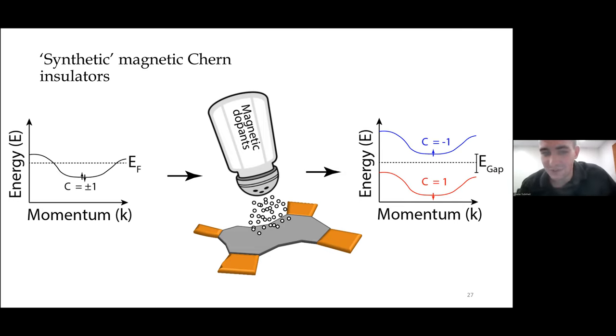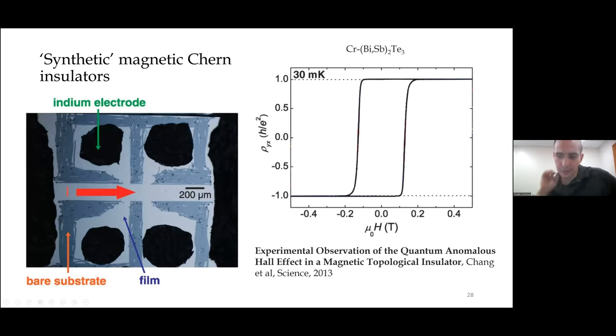So what do I mean by synthetic Chern insulator? So early in the days of the study of these systems, theoretically, there were a variety of proposals for realizing them in experiment. And the first one that ultimately succeeded was this so-called magnetic doping idea. The idea there was to take a 3D topological insulator, make a very, very thin film of it, and add magnetic dopants. So sort of extrinsically turn the system into one that has strong exchange interactions, thereby realizing a Chern insulator. So the idea here is that you start with Chern bands, add your magnetic dopants, which are now incorporated into the lattice, and realize a quantum anomalous Hall effect. And this was very successful. So there are a variety of different groups now that have replicated quantum anomalous Hall effects in a variety of magnetically doped 3D topological insulators in the thin film limit, right?